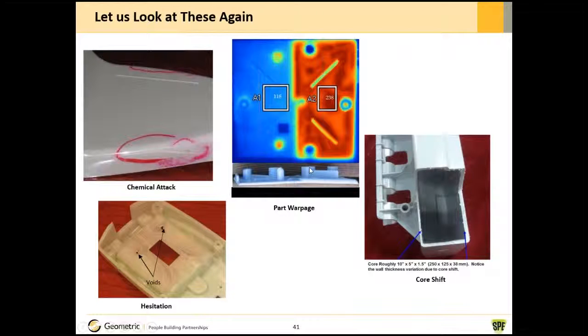Warpage. Oh yeah, poor cooling of the mold. No, the molder did as good as he could. You caused the problem with thin and thick sections right next to each other. This wall being uneven. Oh yeah, they used poor quality steel that didn't have the modulus that the steel should have had. Wrong. The steel was right, with the right modulus. You caused the problem by making the core length way longer than the core width.